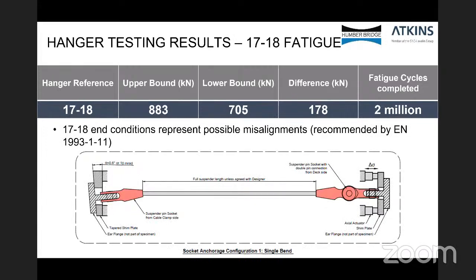This shows the test setup. Because of the possible misalignment between the cable and the sockets, this was included within the test by causing a misalignment of the socket by 0.6 degrees, as can be seen to the left-hand side of this. And this is also recommended by BS EN 1993 Part 1 when carrying out the construction of new bridges. We'll look to the next slide.